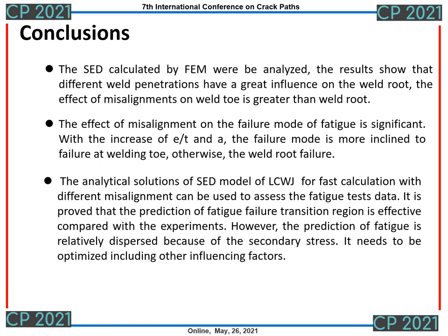The second conclusion is that the analytical solutions of the SED model of LCWJ allow fast calculation with different misalignment and can be used to assess the fatigue test data. It is proved that the prediction for the fatigue failure transition region is effective compared with the experiment. However, some of the predictions deviate because of the secondary stress. It needs to be optimized, including other influencing factors. Thank you for your attention.